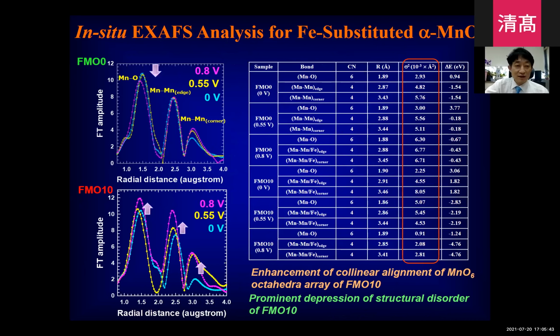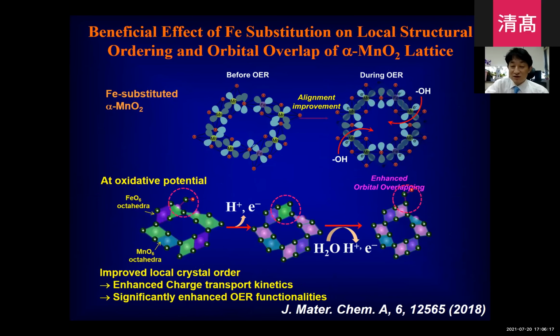We do the in situ XAS analysis, as you can see here. In case of the undoped one, there's a little change of the FT intensity, but it is not very significant. But in case of the iron doped one, we observed a significant enhancement of the FT peak, especially for the corner shell. The increase of the peak intensity is much more dramatic. So we believe this is due to the focusing effect in case of the collinear structure. The multiple scattering path shows focusing effects in case of the collinear geometry. We observe such a remarkable enhancement of the FT peak.